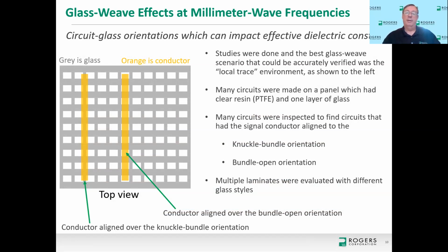And what we did was we inspected a lot of circuits, and we chose circuits that had a very precise orientation between the signal conductor and the glass. The two orientations we were looking for were the knuckle bundle orientation and the bundle open orientation. And then we made comparisons by measuring circuits with these different orientations and a lot of different kinds of measurements, which I'll show in just a few slides. Also, as part of the study, we did this with multiple different laminates that used different glass styles. So we had laminates that were just PTFE and glass only, so it's just pure resin and glass only, but we used different glass styles looking for differences in the glass weave effect.